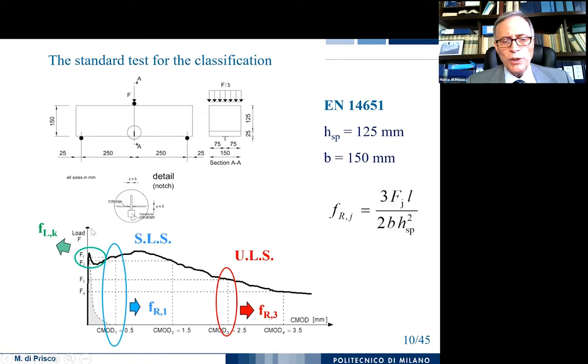And in this case, looking at the load versus CMOD, the crack mouth opening displacement measured at the bottom of the specimen, we could see the force, which changed completely the behavior with respect to the plain concrete. In gray, you see the plain concrete response, and in a continuous black line, you see what happens when you have a certain amount of fibers, around 40 kilograms of fibers.